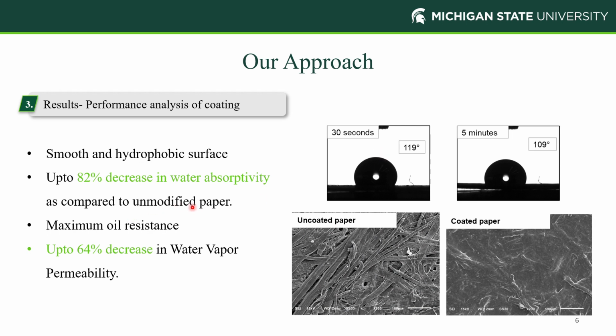So we saw about an 82% decrease in water absorptivity, which was measured using the Cobb test. As compared to the unmodified paper, it shows excellent oil resistance, and we also measured the water vapor permeability, and we saw that it reduced by 64% as compared to the unmodified paper.